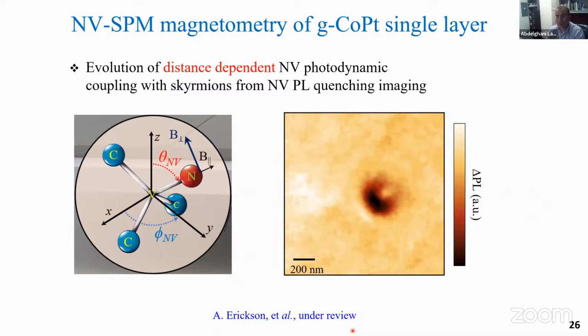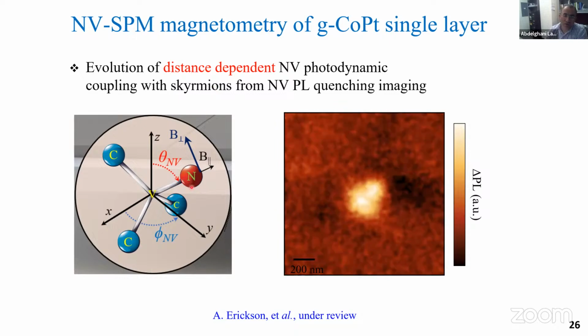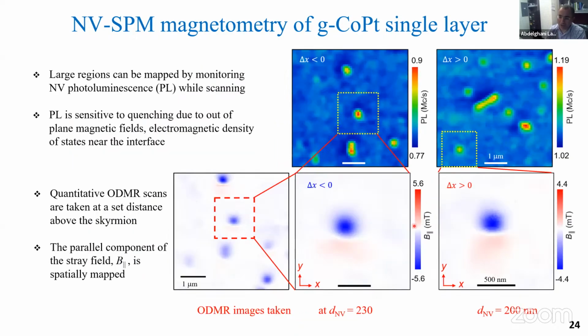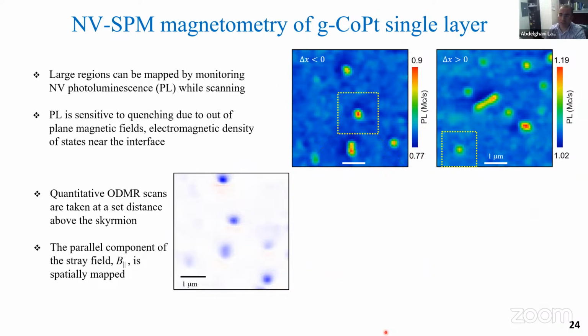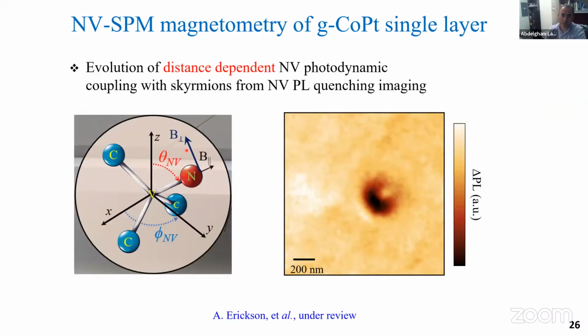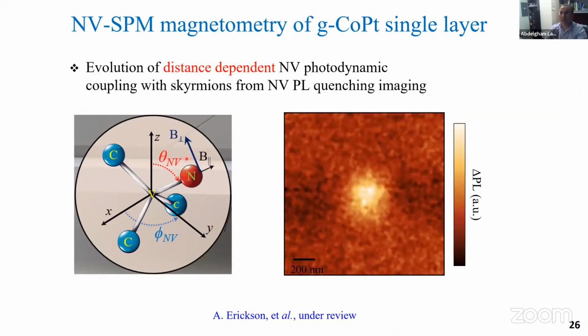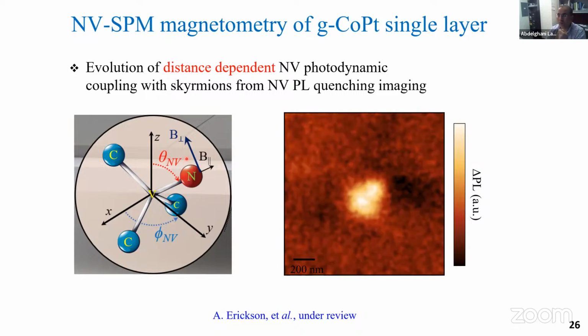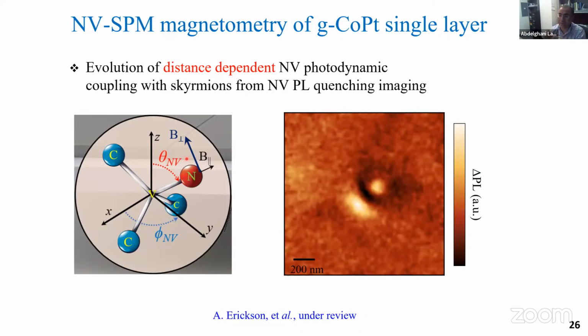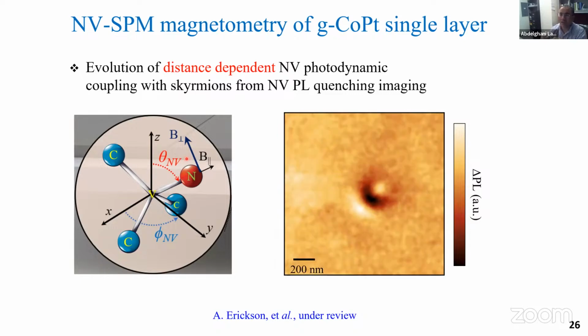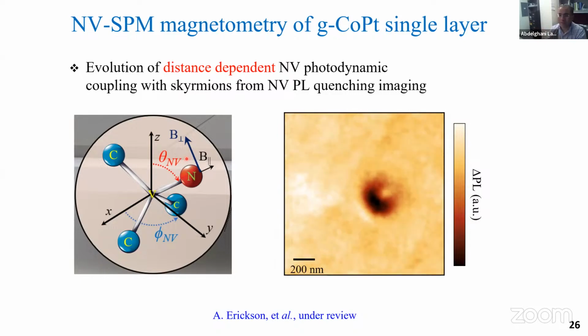But again, when you use fluorescence quenching, because these spin textures generate a high magnetic field, even as you get the NV closer and closer, these skyrmions generate an in-plane or transverse field. The transverse field can somehow mix the excited state and therefore lead to a change in the photoluminescence.